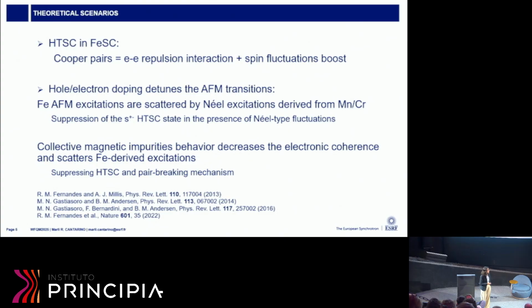When you dope, you can understand the suppression of the magnetic transition in different ways. There are different scenarios. In one of the scenarios, you see antiferromagnetic excitations scattered by the Neel excitations introduced by the dopants. So you have a competition of different natures of excitations in this case, and these excitations will be the ingredient that suppresses the S-plus-minus superconductivity in these materials.